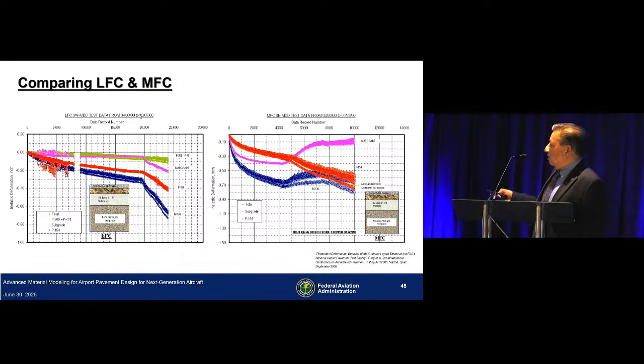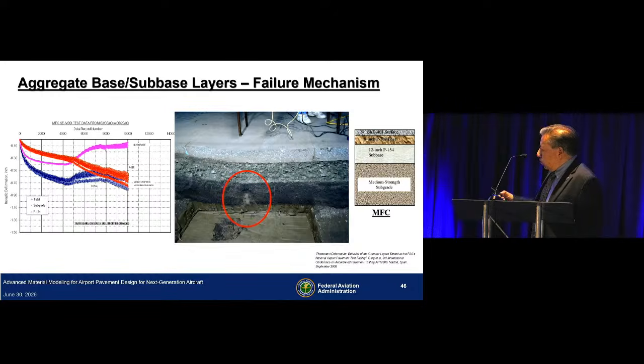It's a very different behavior in your medium strength subgrade test section. Your deformation in the subgrade is much higher compared to your base or subbase layer. This is your subbase layer. And something happens around 5,000 passes. As you can see, we see the change in the curve. And once we fail these sections, we generally cut trenches to look at the failure mechanism of what was happening. And what we saw was failure in the subbase layer with subgrade intrusion into the subbase.